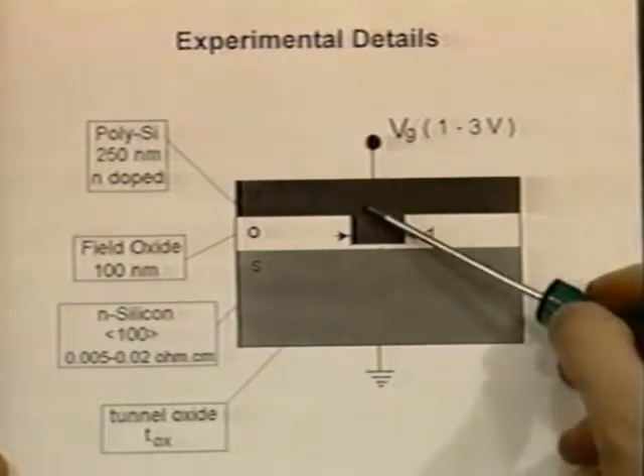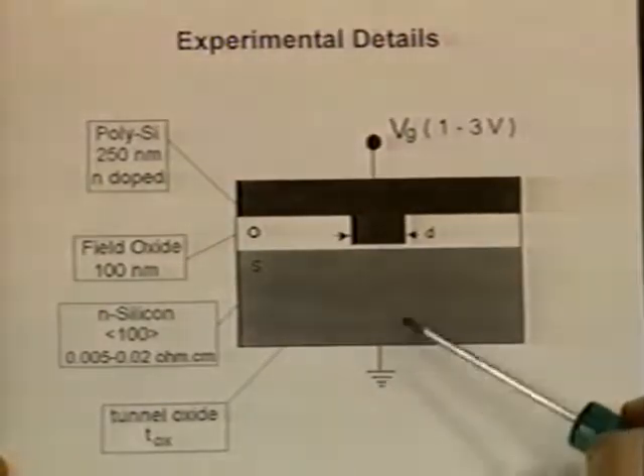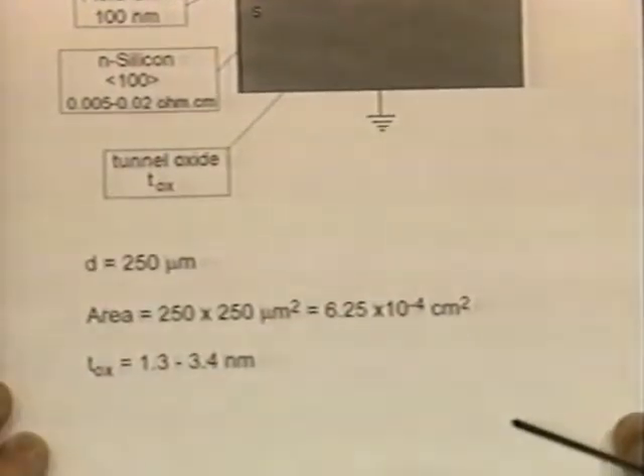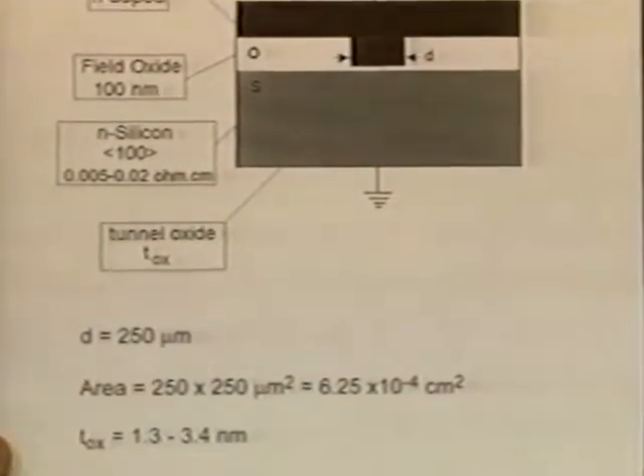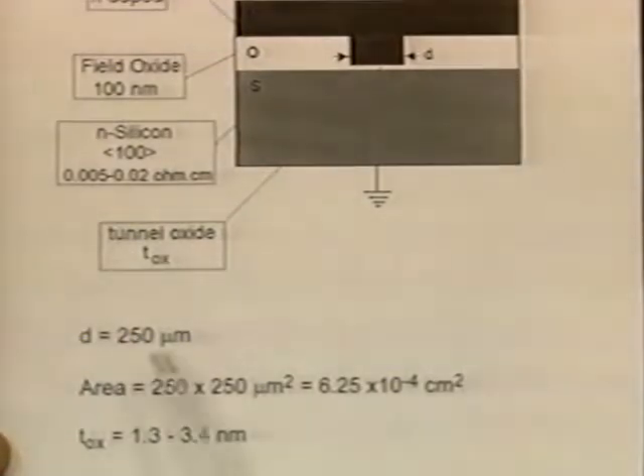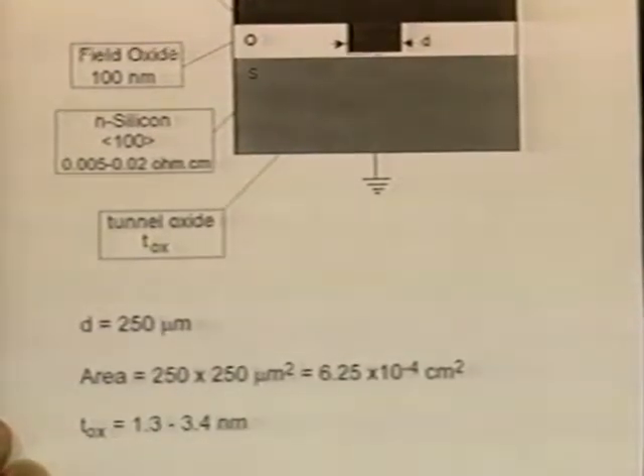In that case, you put a negative voltage here and you inject electrons towards the silicon, and I'll talk about damage that takes place for both types of injections. The device size that I'll be talking about, D, the diameter of the device, is 250 microns, which is a pretty big area, but I've also looked at devices down to a micron square or even smaller, and I'll tell you about some results comparing larger area with smaller area devices. And again, the thicknesses range from 13 to 34 or 35 angstroms.